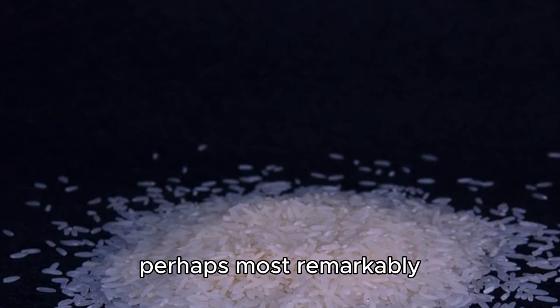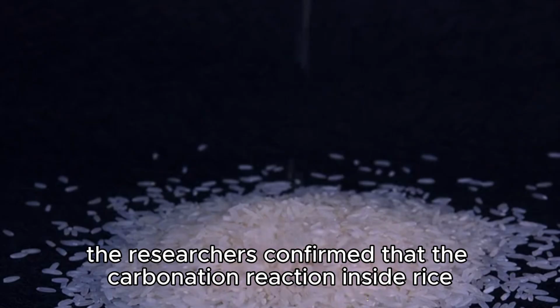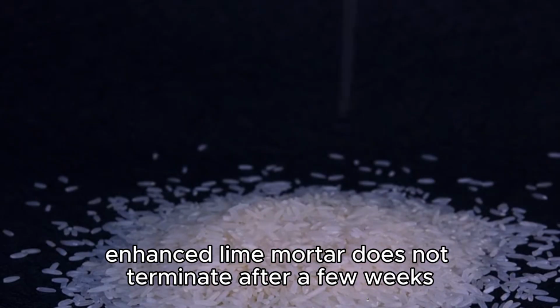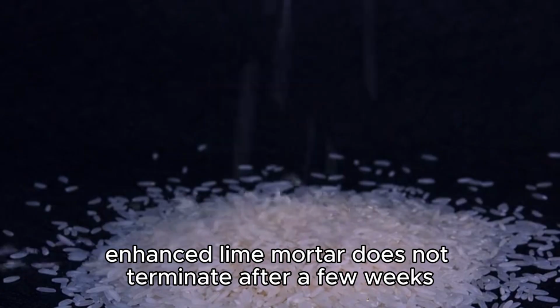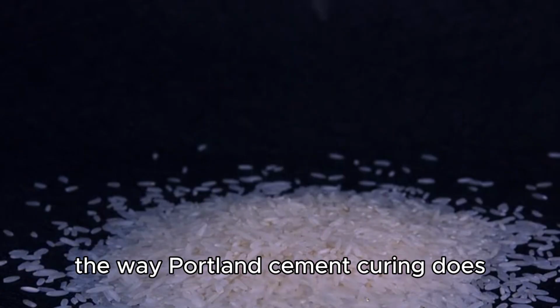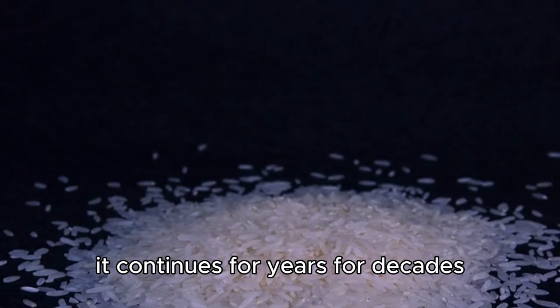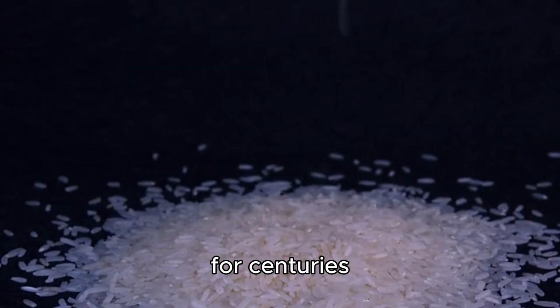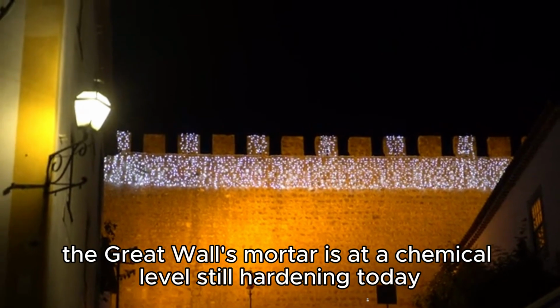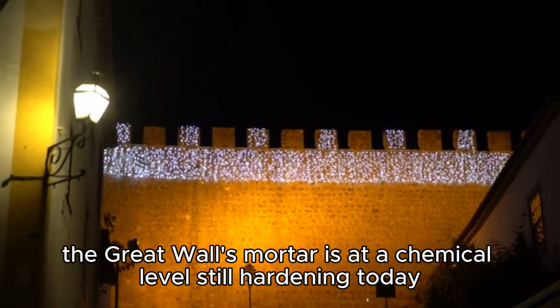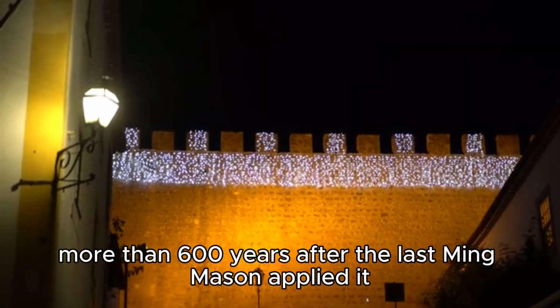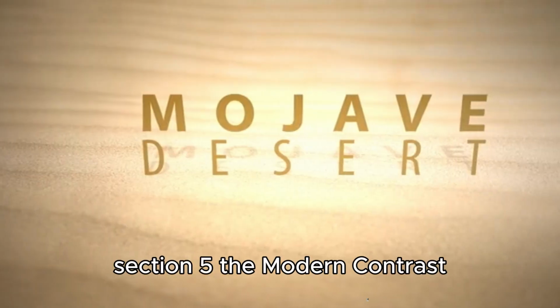Perhaps most remarkably, the researchers confirmed that the carbonation reaction inside rice-enhanced lime mortar does not terminate after a few weeks the way Portland cement curing does. It continues for years, for decades, for centuries. The Great Wall's mortar is, at a chemical level, still hardening today, more than 600 years after the last Ming mason applied it.